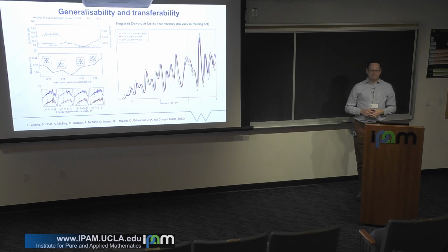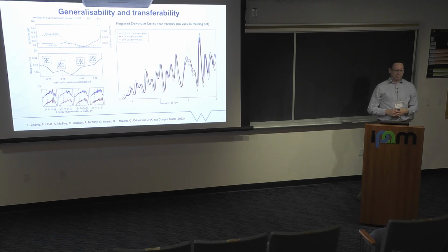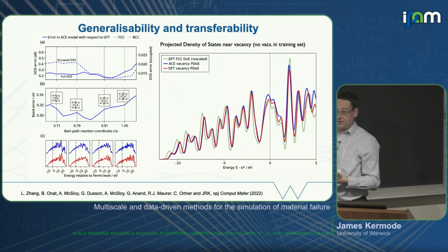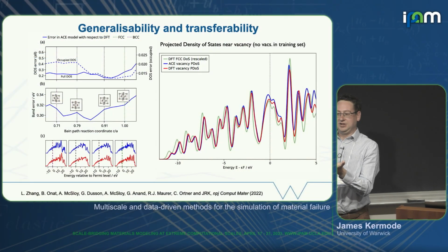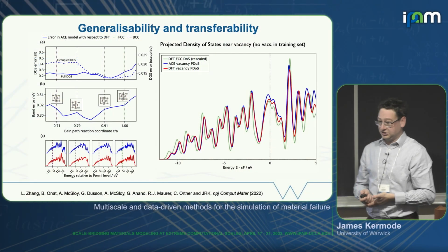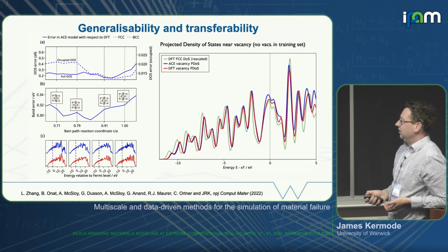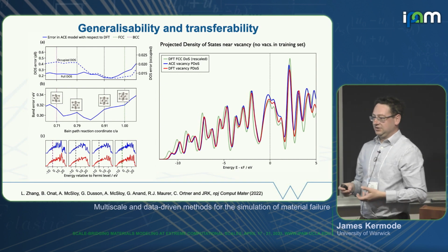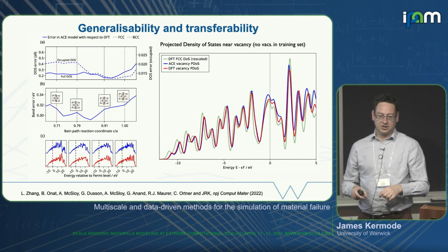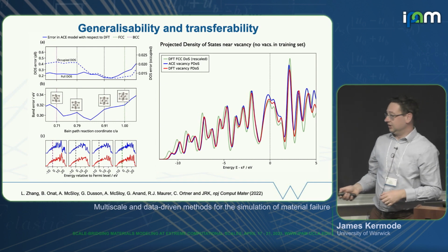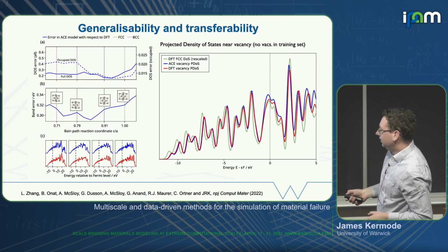We'd only trained this model on bulk, but we wanted to see how it would perform on a defect. The training data was 500 Kelvin MD, so atoms were jiggling around a little bit. And actually, when we put a vacancy in and made a prediction for the projected density of states, so a probe for the electronic structure for the nearest neighbors of that vacancy, they come out pretty well.